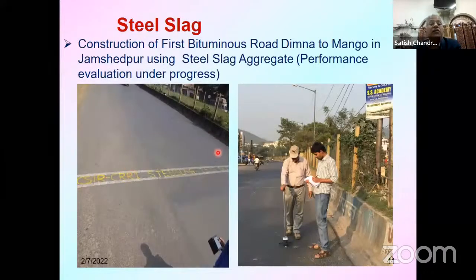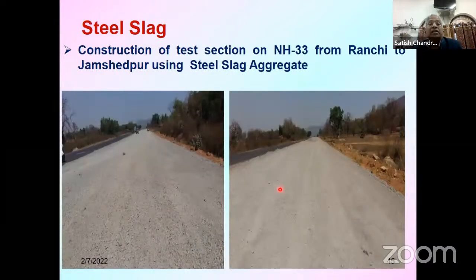Now, steel slag coming out of steel industries. Using steel slag, CRRI constructed a test track on the Dimna to Mango road in Jamshedpur using steel slag aggregate, and performance was evaluated and it was fine. Similarly, another section was made from Ranchi to Jamshedpur on NH33 using steel slag. And an important point is that steel slag is very heavy, and therefore the requirement of bitumen is also low.